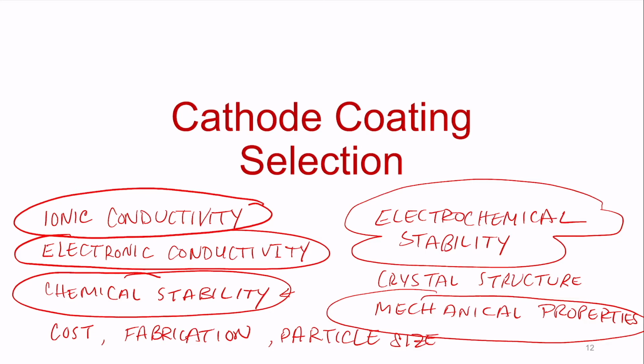And of course, if your ions are not moving, they're not moving, right? If it's not ionically conductive, then lithium migration has a higher energy barrier. If the activation energy is high and ionic conductivity is low, then obviously that's also not a great starter. So these are the properties that you can screen by, because we can map out all of these through DFT